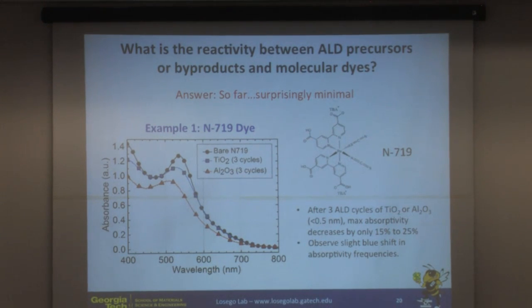Most of these reactions occur well below 200 degrees Celsius, so we're not hurting the organic molecules thermally, but we were concerned with reactions between our vapor phase precursors and the surface bound molecules. So this is an example here of a common dye molecule used in DSSC devices, N719. This is the molecular structure here.